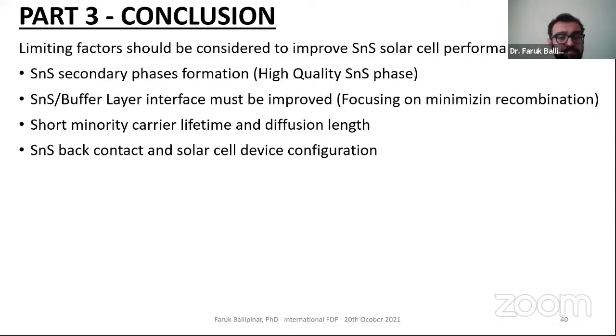Another problem is the tin sulfide buffer layer interface between the cadmium sulfide, cadmium oxide, or other types of N-type materials. The band offset and interface analysis must be improved. So the researchers need to focus on minimizing the recombination between these two layers. And short minority carrier lifetime and diffusion length is still a problem for the tin sulfide material by itself.